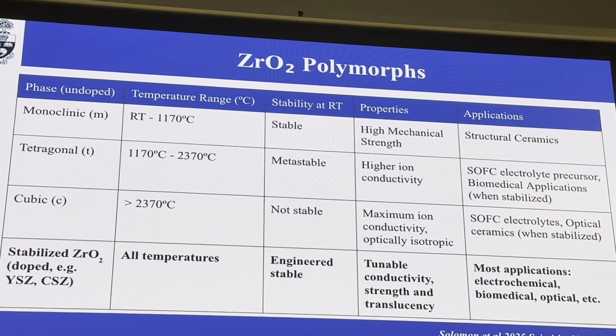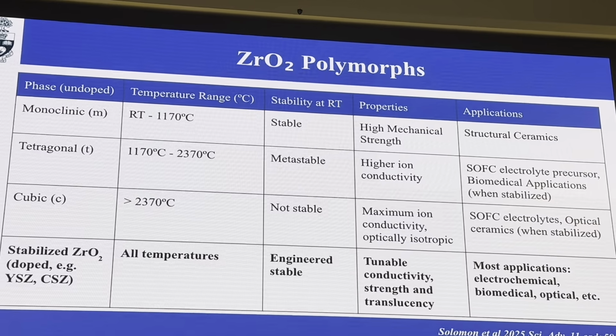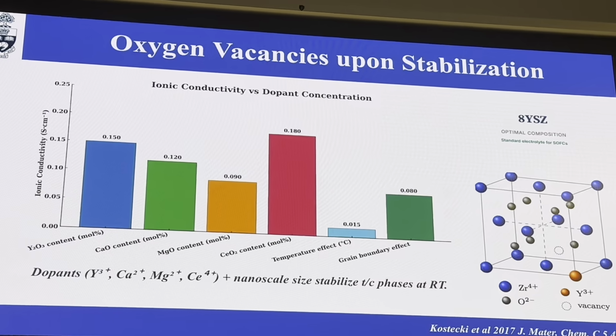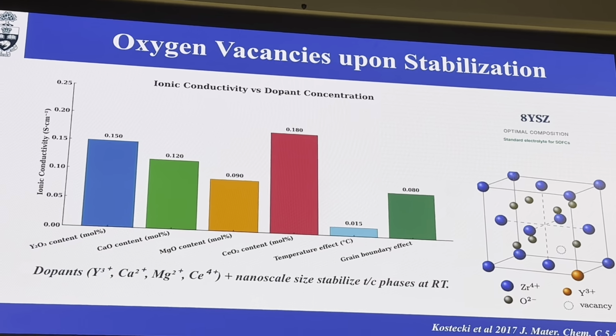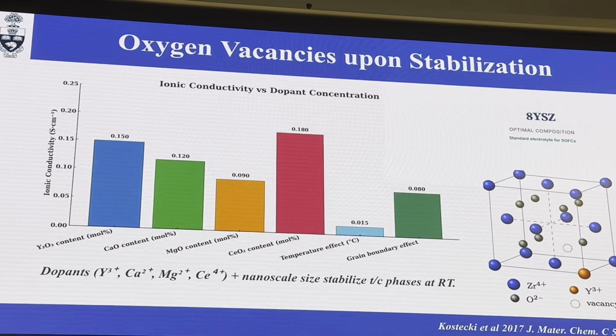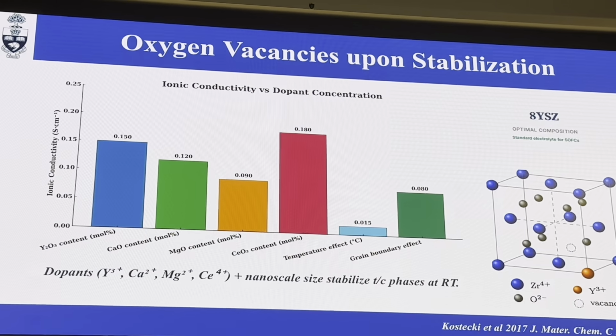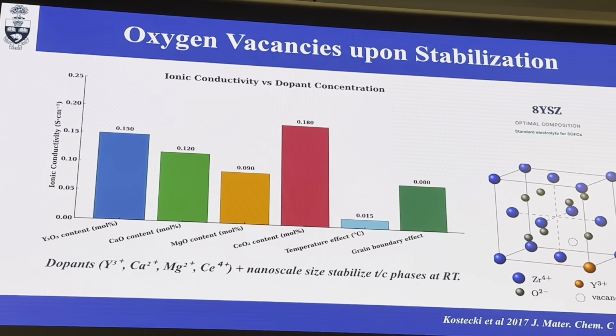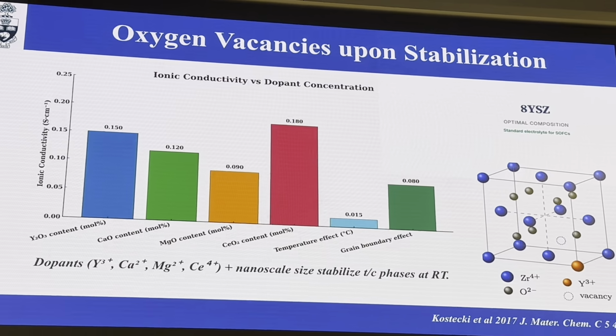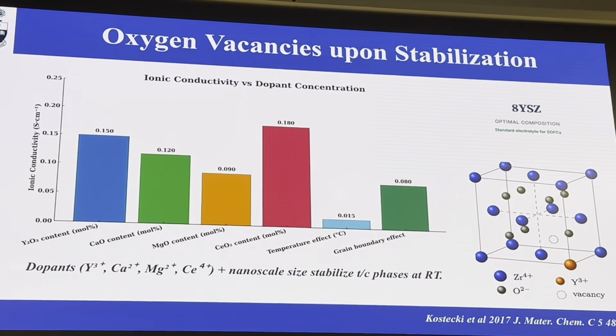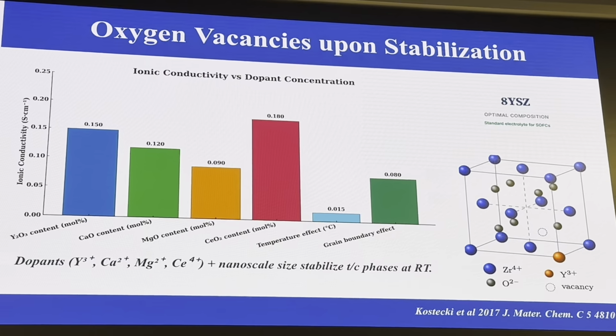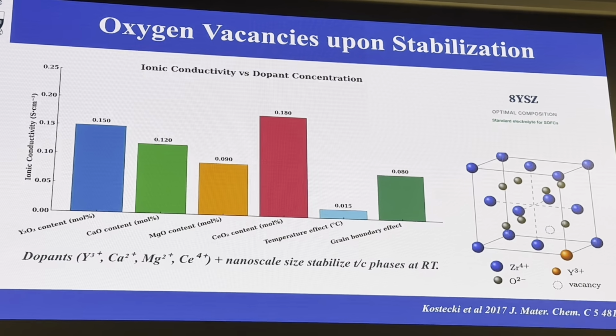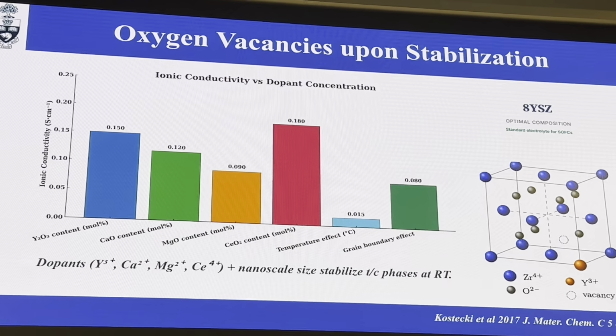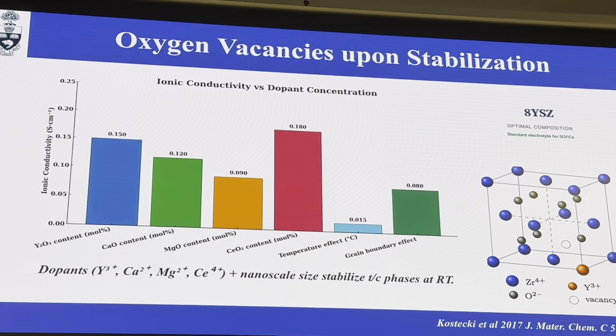Now, a remarkable thing happens to the lattice when those dopants are added. Take yttrium as an example. Zirconium is normally tetravalent, meaning each zirconium ion has a +4 charge. On the other hand, yttrium is trivalent and has a +3 charge. So when yttrium replaces zirconium in the lattice, there is a missing positive charge that needs to be balanced. The crystal compensates by expelling an oxygen ion, creating what we call an oxygen vacancy.